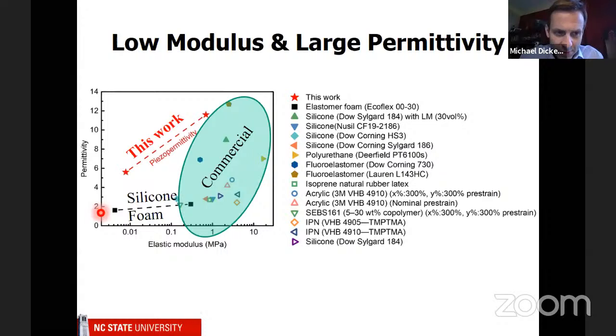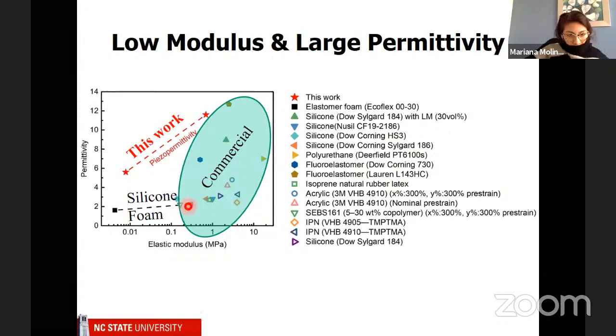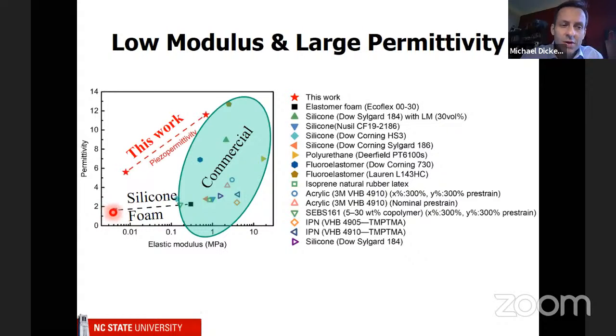Okay, so in the end, what we found was that if you look at the permittivity of the material, let me start over here. These are commercial silicones. So this is their modulus, sort of how stiff they are. If you make a silicone into a foam, you lower the modulus, but it's got a very low dielectric constant. So by adding the liquid metal, we were able to make the dielectric much higher. So this is also quite exciting.